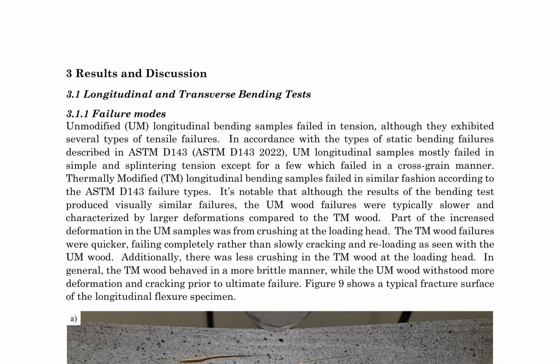Longitudinal and transverse bending tests were conducted to investigate the failure modes and mechanical properties of unmodified and thermally modified wood samples. The unmodified longitudinal bending samples exhibited various tensile failures, including simple and splintering tension, as well as cross-grain failures, in accordance with the ASTM D143 standard. In contrast, thermally modified longitudinal bending samples failed in a similar manner but with notable differences in failure behavior, characterized by quicker, more brittle behavior, with less crushing at the loading head and less deformation prior to ultimate failure.